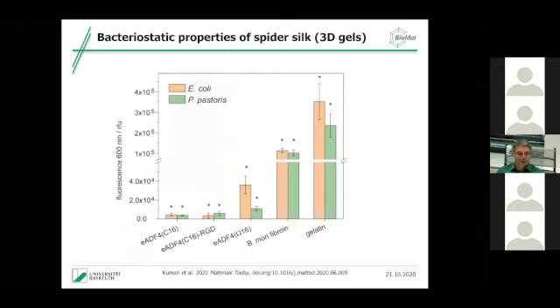Now let's go back to our bacterial story. So I showed you that the surface of the silk is microbe repellent. How about now in the hydrogels? Because if you have here a bacterial manifestation, that could also be very severe. And you can see very nicely that, again, our spider silks, and here you see our working horse with RGD, they actually see no bacteria or yeast manifestation. In contrast to gelatin, which is very often used in 3D printing and biofabrication, and Bombyx mori fibroin, so silkworm fibroin, that does not have these repellent features.